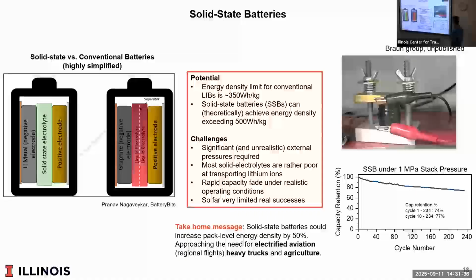It turns out that the best solid-state batteries right now operate between 10 and 50 MPa pressure. So that basically means your battery is living within a hydraulic press. That's not realistic. So we need to reduce that. And there's other problems. And so here's one we've made. Our big goal has been to reduce the pressure. And so now we're down to 1 MPa, which is probably doable, but that's still a meaningful pressure.